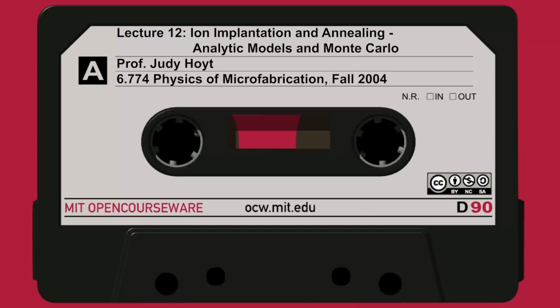In fact, what people were trying to do was also cover the wafer with an amorphous material. People thought, oh, well, why don't I put a layer of something amorphous? That'll prevent channeling, right? Because I'm covering up the crystal with this amorphous material. But in fact, it doesn't really avoid channeling. Putting on a little bit of nitride doesn't really help. You still get this so-called exponential channeling tail. You see all 4 profiles have this exponential tail.